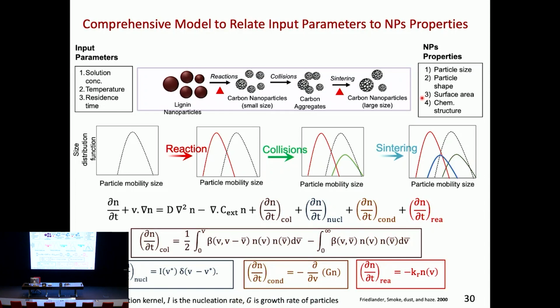But in addition to this, I have a reaction term which I have to toss into this equation, right? So I need to study that. And I really want to study sintering. So you see what is sintering? It's shown at the bottom. Two particles collide, and then they slowly merge into a single particle, right? There's a driving force that tells me I want to become a spherical shape because it's the minimum area. But depending on the time, I will be in some intermediate state.